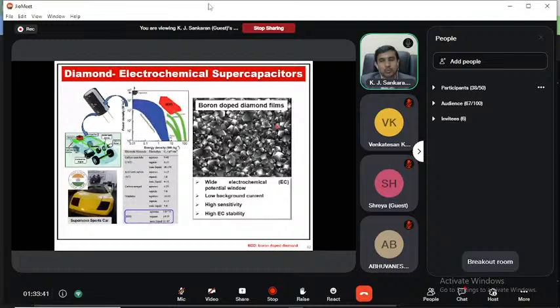Here I talk about the boron doped diamond because it's p-type. That is especially for the electrochemical supercapacitors, having a very good potential window. But nitrogen incorporated diamond, which is n-type, goes for the electronic applications. The boron doped diamond has a very good potential window, low background current, high sensitivity and high electrochemical stability compared to the other carbon-based materials, which makes boron doped diamond a very good electrochemical supercapacitor electrode.